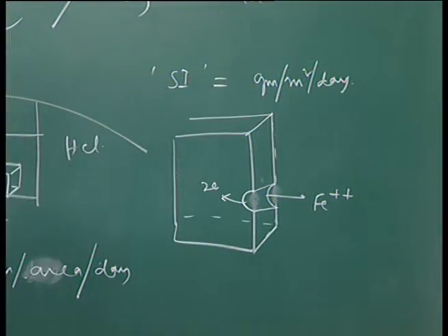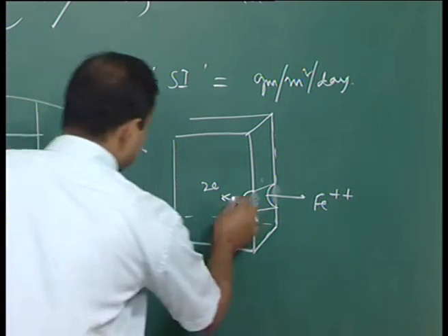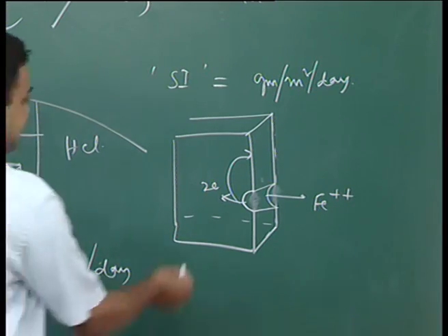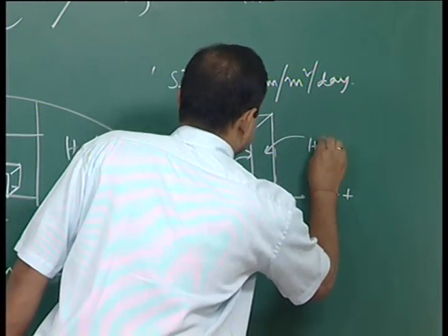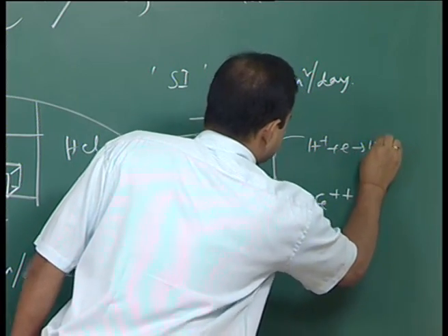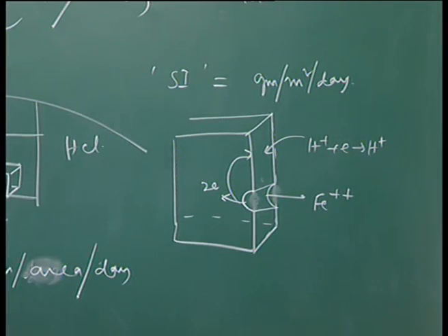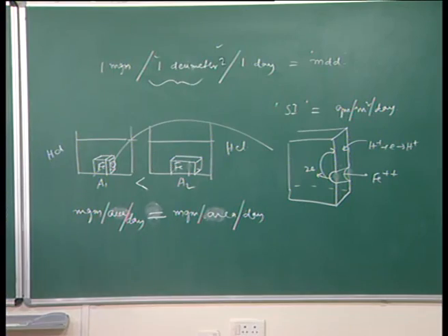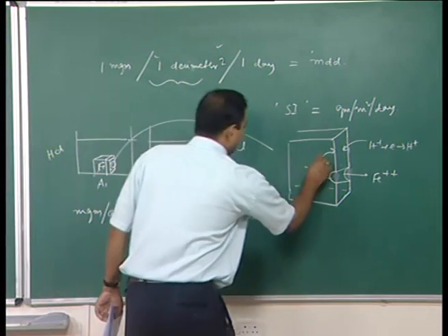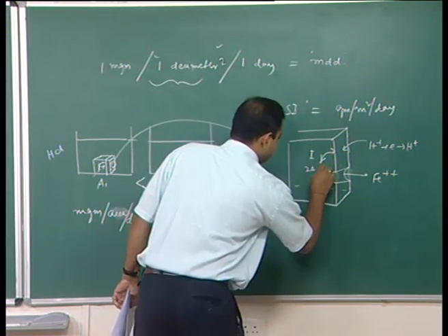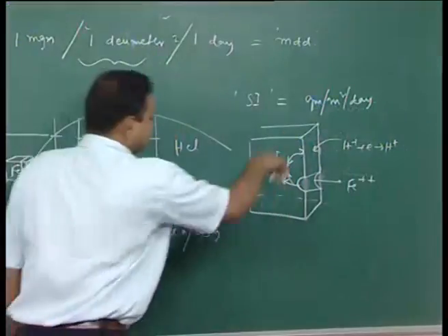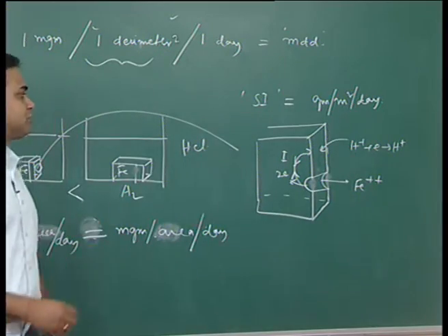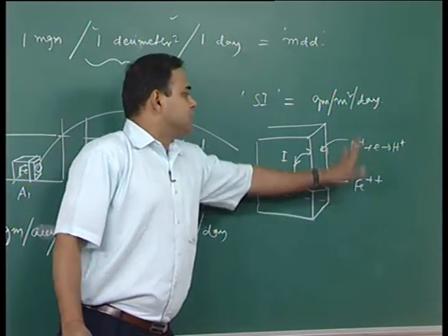These 2 electrons will go through the metal piece to a section where you have the cathodic reaction. Now that means electron is flowing from the anodic section, and current flows in the opposite direction. So the current flow would be in this way. If electron flow is this way, current flow would be the reverse way, and then you have a circuit. In the solution, the current will also flow from the anodic side to the cathodic side.